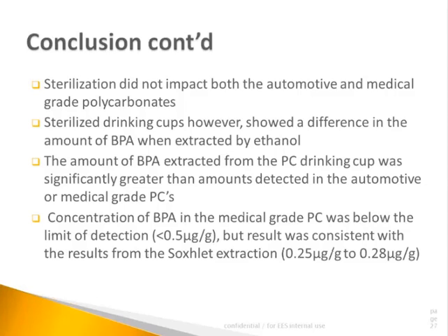As a note, sterilization did not seem to impact the medical and automotive grade polycarbonate, but the consumer grade did, however, show significant shift when the drinking cups went through sterilization followed by ethanol extraction. This behavior could be explained from the fact that most consumer grade material may not have been formulated for gamma resistance. Next slide.